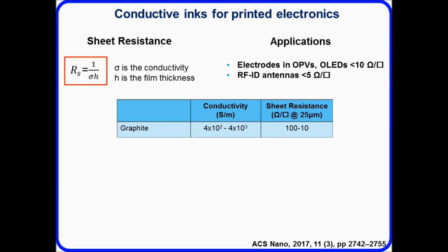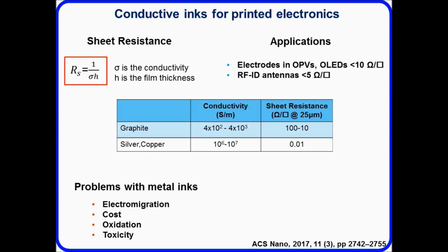So looking at traditional graphite-based conductive inks, these give a sheet resistance normalized to 25 microns of around 10 to 100 ohms per square. If we look at metal-based inks, so silver or copper, aluminium-based inks, we can achieve down to around 0.01 ohms per square, so much higher conductivity. But there are issues with electromigration. There are cost issues, so silver is very expensive. Copper often oxidizes with time, and so it may degrade. And also there are some toxicity issues, so recycling these materials is not so straightforward. They cannot just be thrown away as they will lead to some environmental toxicity.